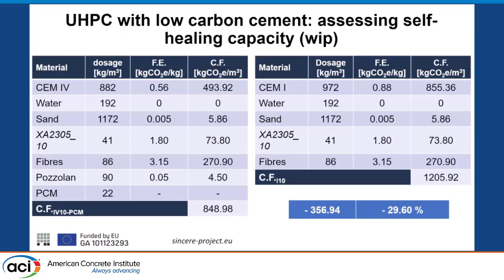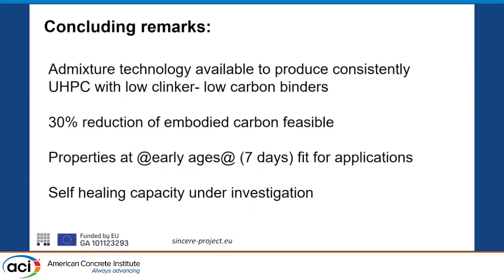The target was that we wanted a 30% lower carbon footprint. This is simply based on the environmental product declaration of the constituents. So this is just, I would say, the preliminary step, but going from CEM I to CEM IV and adjusting this, we got an improvement in terms of carbon footprint, considering the original composition and the new one, which is complying with our requirements.